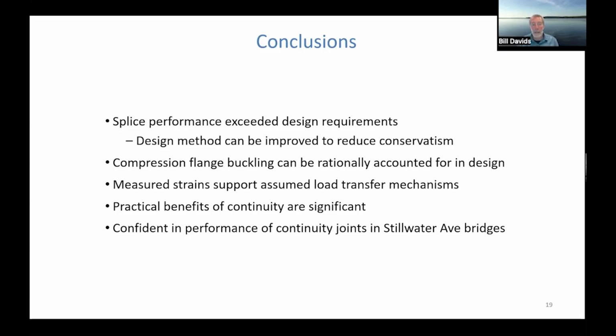And at the end of the day, we can be very confident in the performance of the continuity joints in the Stillwater Avenue bridges. And I was very happy when this test was completed successfully because we actually designed those continuity joints and the girders had been fabricated and were all spec'd out before we actually tested the continuity joints. So I'm really glad that the test supported the design of those bridges.